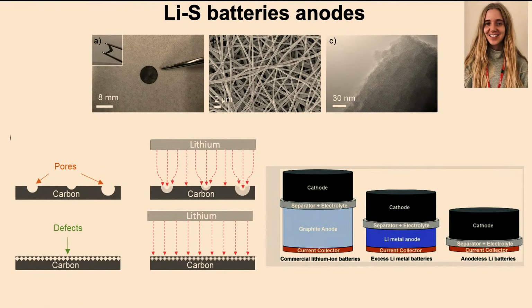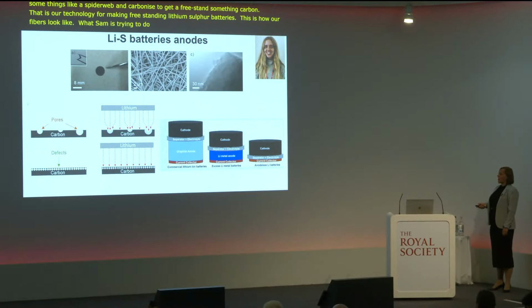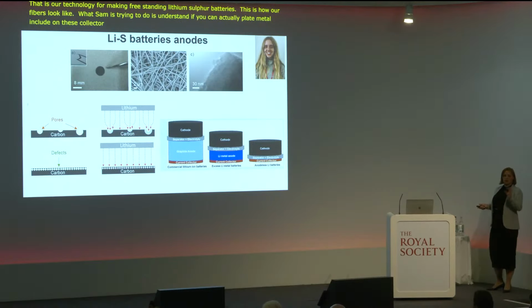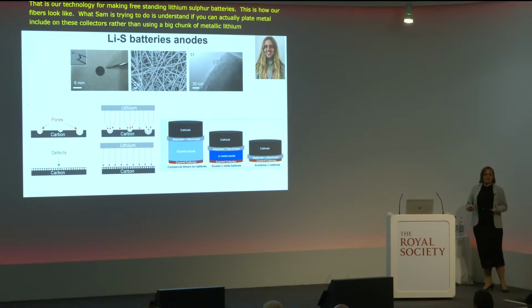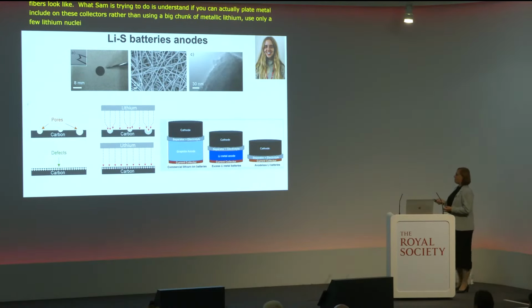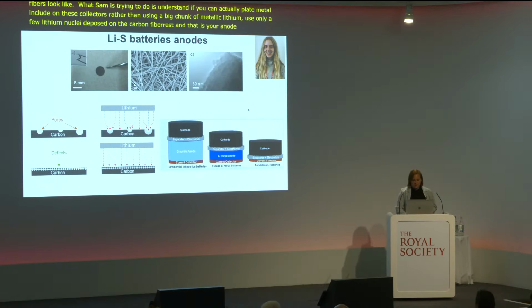So this is how our fibers look like. What Sam is trying to do is to understand if you can actually plate metallic lithium on these 3D current collectors in a way that rather than using a big chunk of metallic lithium, you use just a few lithium nuclei deposited on these carbon fibers, and that's your anode. And so you then prevent the dendrite formation and so on. We just started this work.